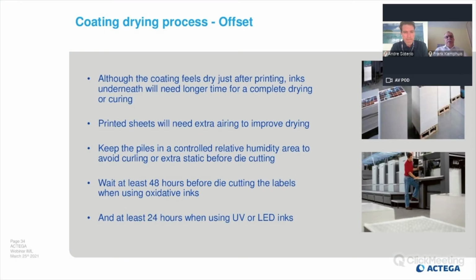Yeah, if the sheets are completed, then keep in mind, if you're using oxidative drying inks, these inks need oxidative drying, so it's also a chemical reaction. And for that, the ink dries slower than the coating itself, and that means for further steps you have to wait 48 hours, and it makes sense to air the sheets well enough, and also control humidity to avoid curling or problems with static charging before the cutting is done.